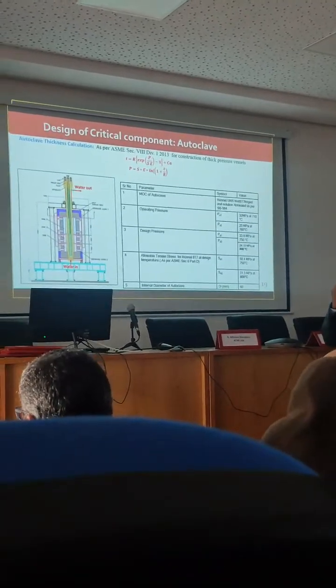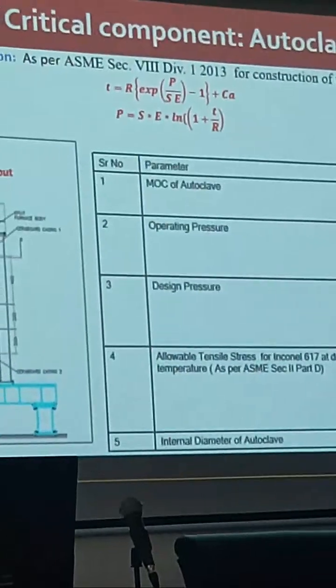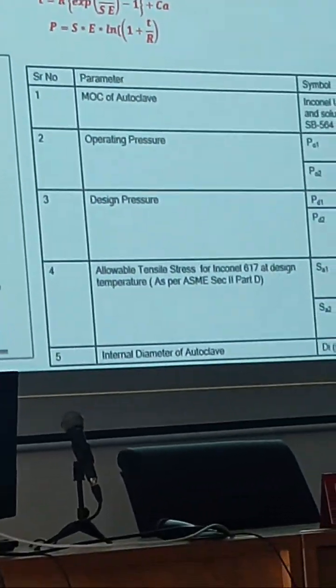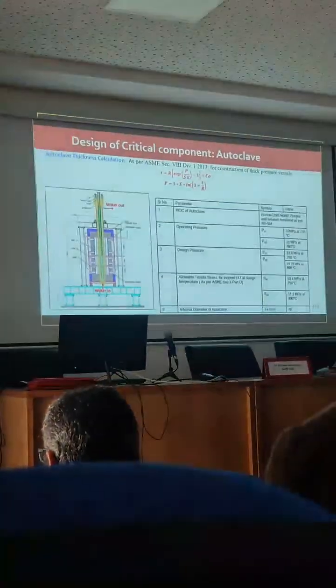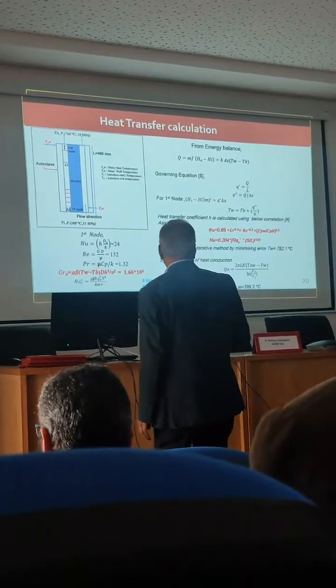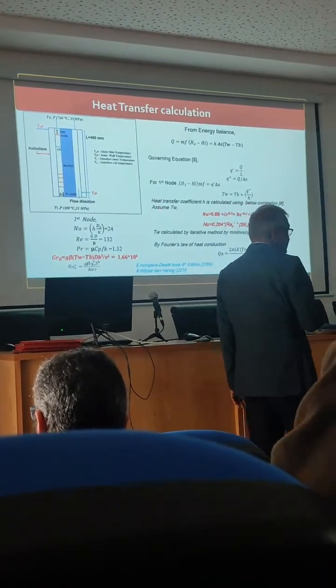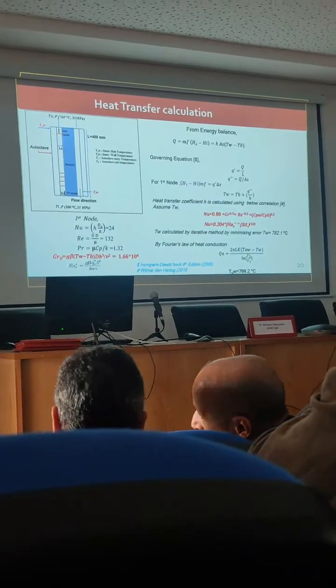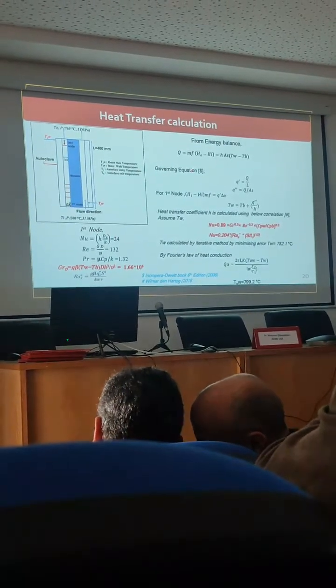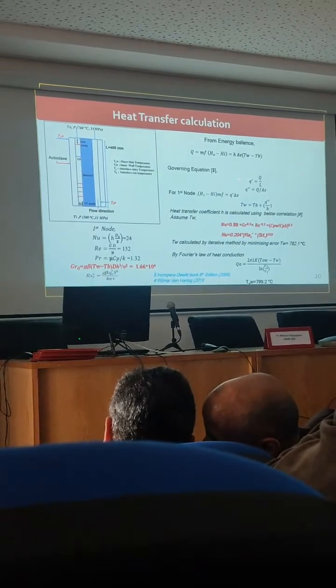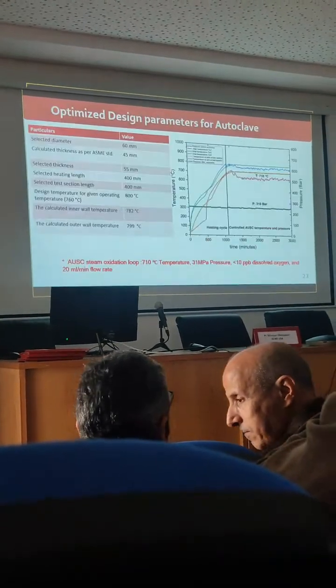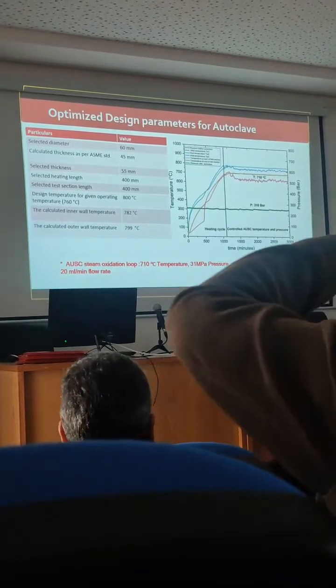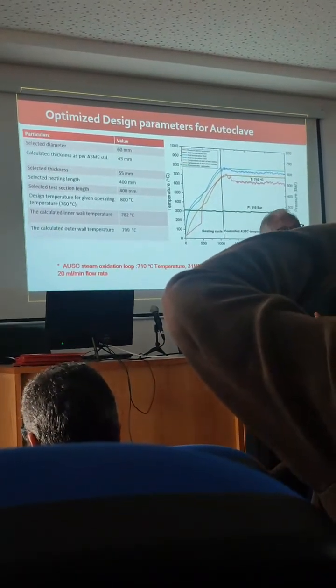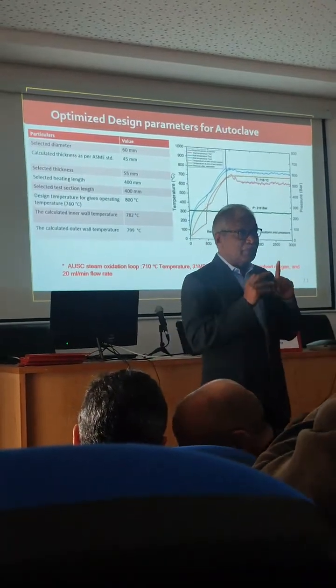So the optimization of the reactor is needed so that you are able to get the temperature and the pressure without any problems. Otherwise, the steel temperature will be very high. You cannot really work on it. So, of course, we collaborate. I don't want to get into these equations again. Most of the mechanical engineering department would know how to calculate all this using these equations. But finally, using all these equations, we were able to arrive at the thickness of the reactor so that the reactor can be very stable and you are able to reach the temperatures. So we have done it.